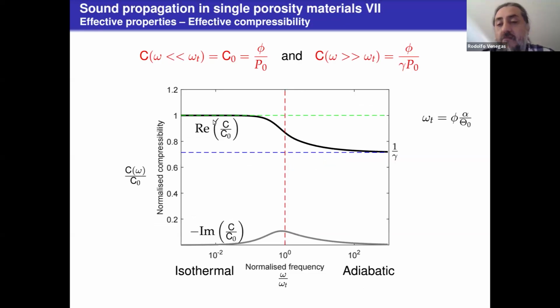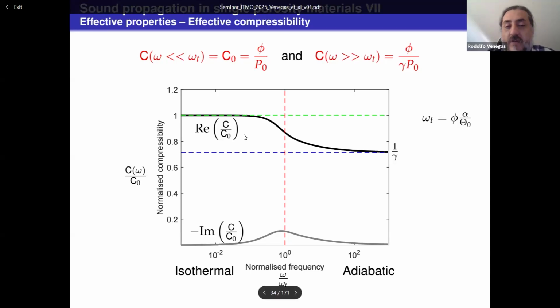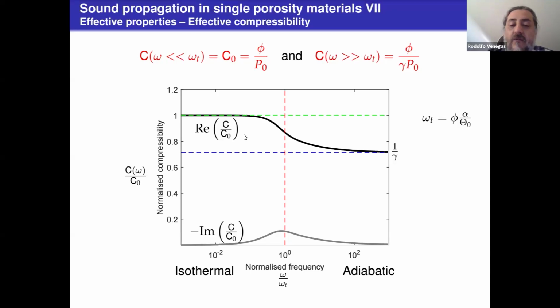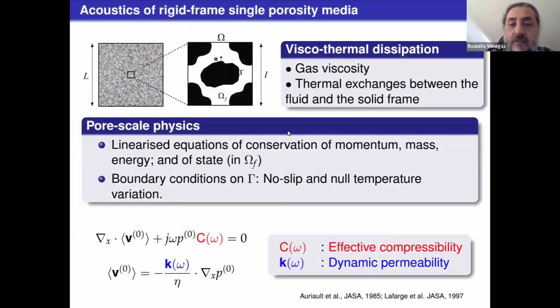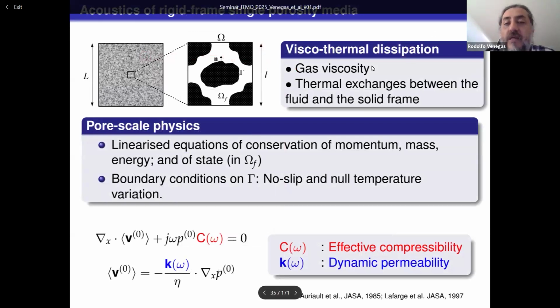We will see that in more complex materials with different physics, the behavior of these two effective parameters will change significantly, and that will help us to control sound waves in different ways. So let us summarize this idea. Viscothermal dissipation in these single porosity materials is due to gas viscosity and thermal exchanges between the fluid and the solid frame. So the pore scale physics are the linearized equations of conservation of momentum, mass, energy, and of state, with boundary conditions of no slip and null temperature variation.